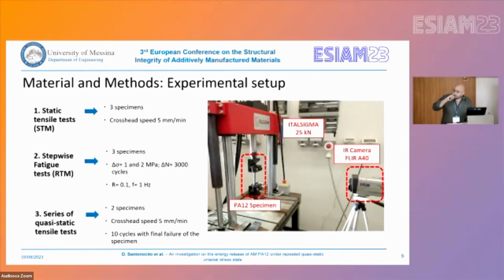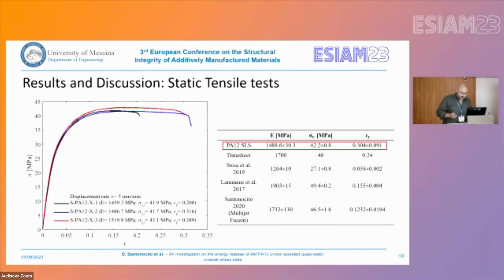And finally, we perform a series of quasi-static tensile tests on 2 specimens with the same parameters as the first series of static tensile tests. We perform 10 cycles for each specimen up to the failure of the specimen. So regarding the static tensile test, I show you here the stress strain curve of the materials.